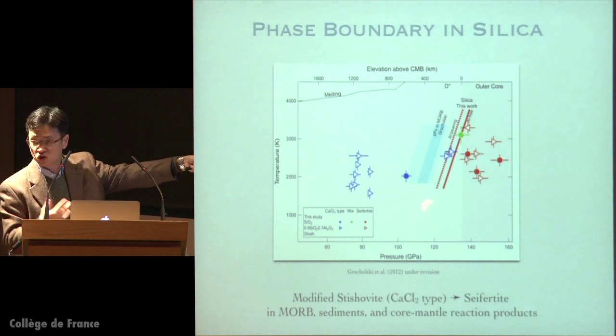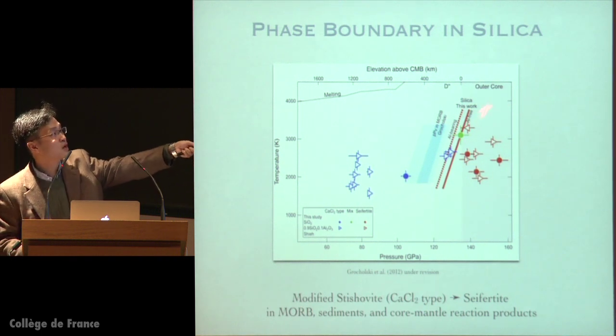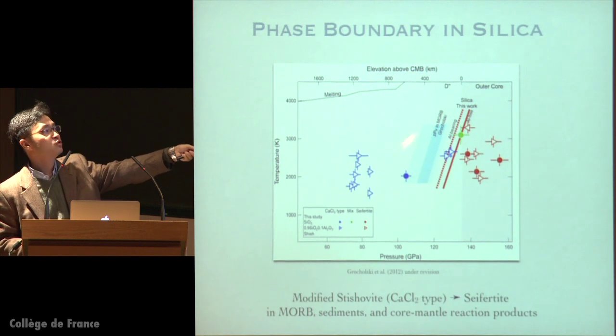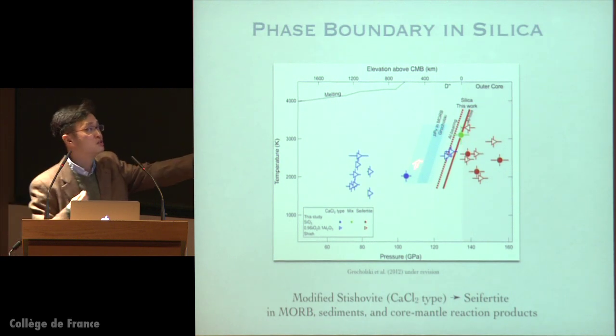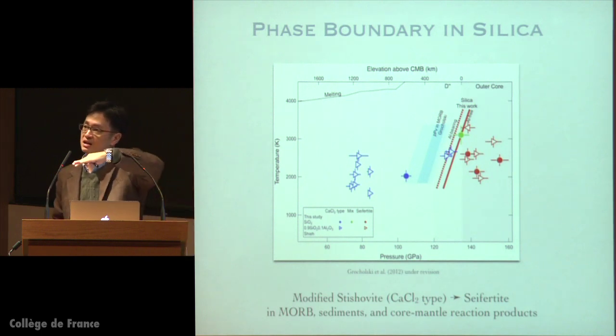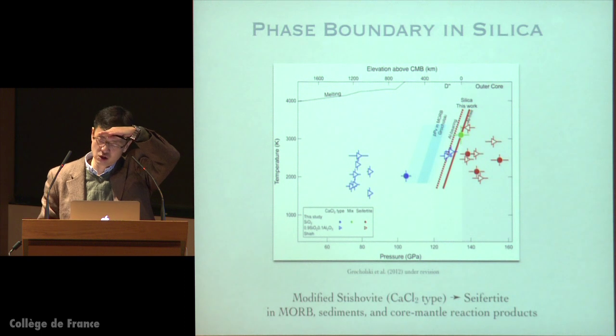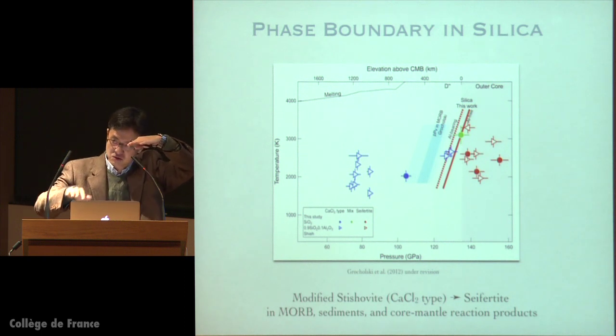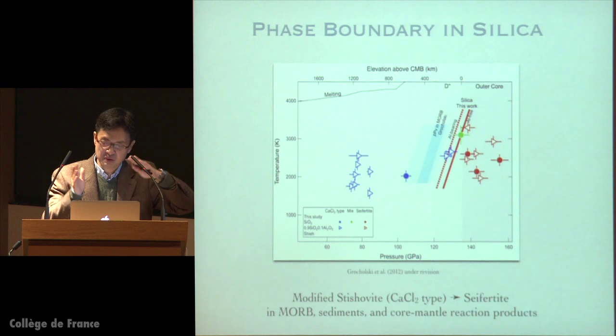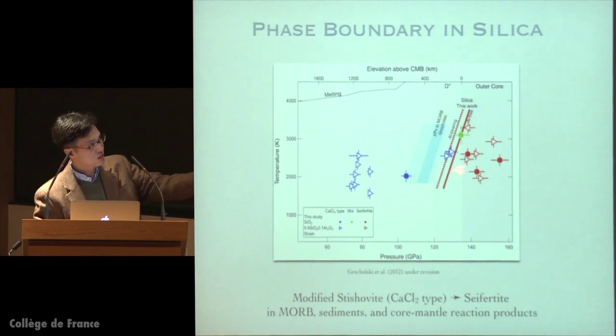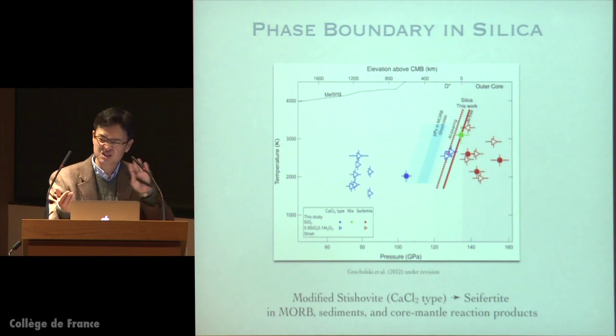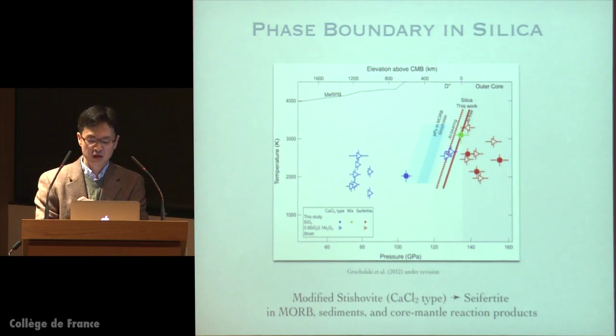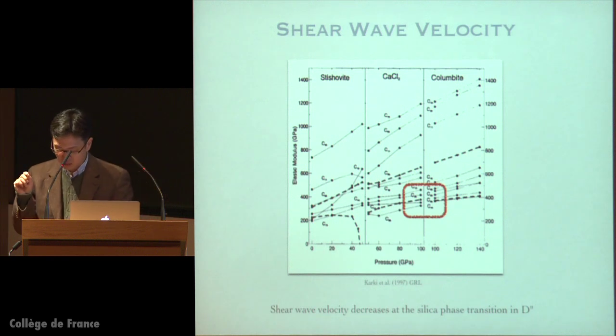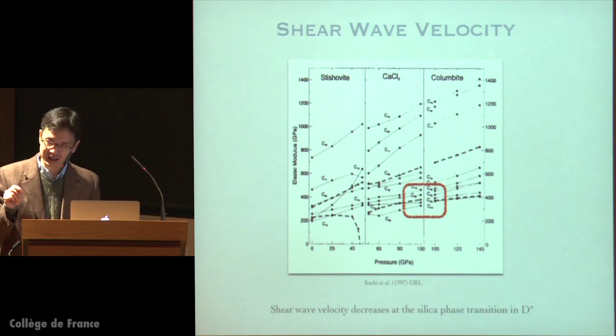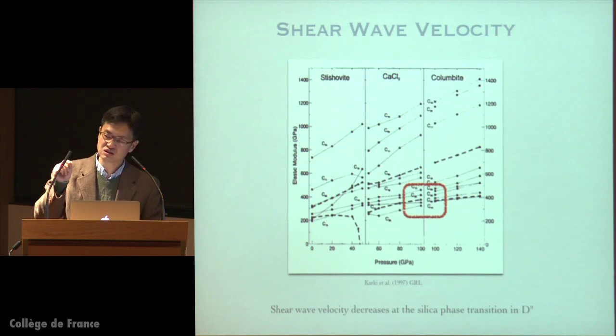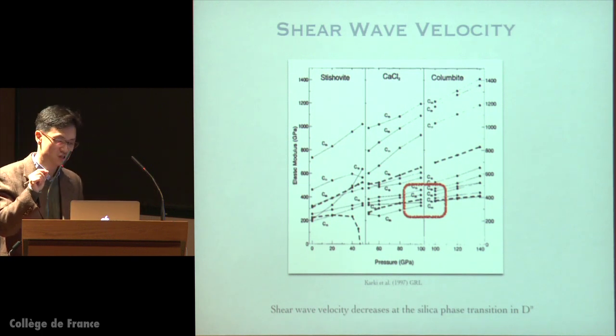So the red line here shows where that silica boundary locates with respect to the post-perovskite transition in MORB composition. So this shows you that the post-perovskite transition is, relatively speaking, shallower, and the silica boundary is, relatively speaking, deeper. Well, it's debatable whether the silica boundary may exist in the mantle or not, because it's so close to the core mantle boundary. But for the sake of discussion, let's, at the moment, assume that it may exist in the mantle. What is clear for us is that it should exist deeper than the post-perovskite transition.